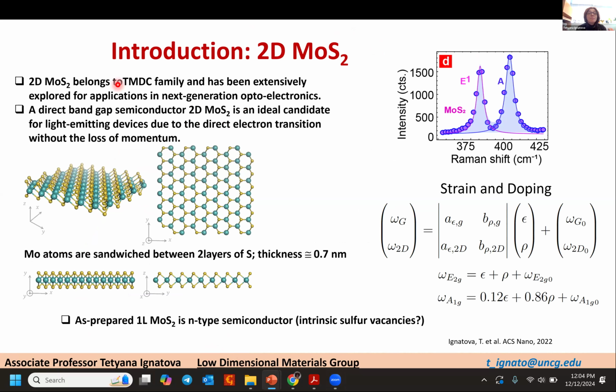Molybdenum disulfide belongs to the TMDC family and has been extensively explored for applications in optoelectronic devices. MoS2 has a direct band gap, and because of it, it became one of the ideal candidates for light-emitting devices. Here you can see just the cartoon for MoS2. The unit cell contains 1 molybdenum atom and 2 sulfur atoms, and the thickness of this monolayer is about 0.7 nanometers. On the right side, you can see the Raman signature of MoS2, typically the in-plane and out-of-plane peaks.